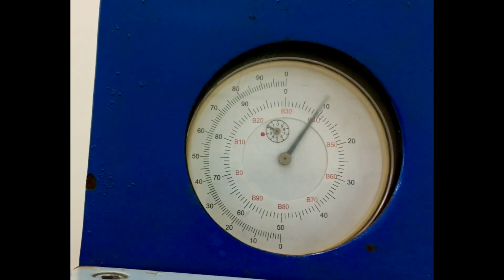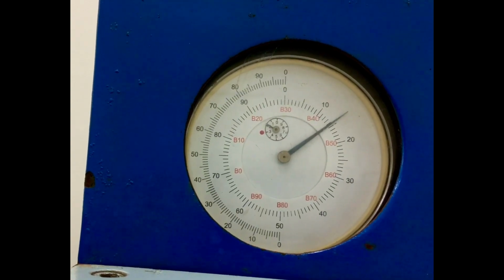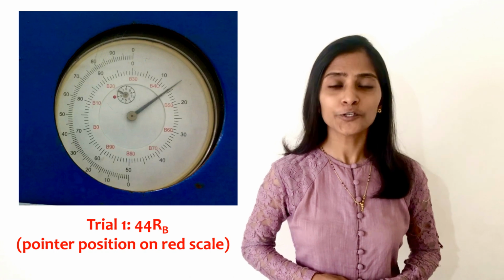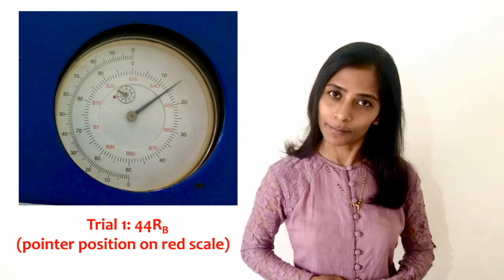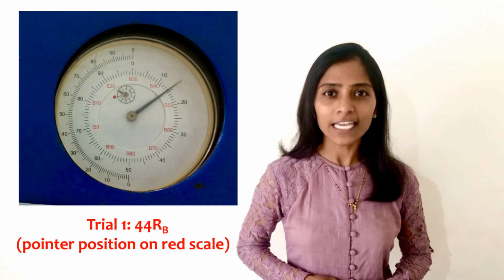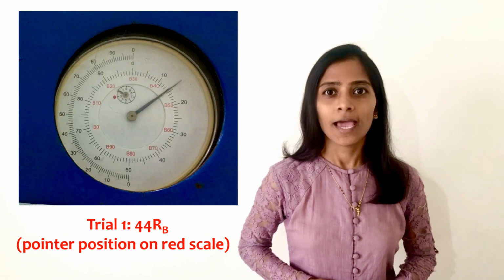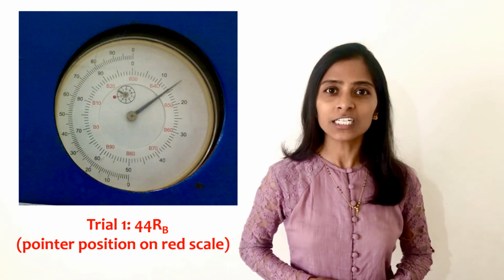After unloading, we have to observe the red scale carefully. According to the first trial, the hardness of the test specimen is 44 RB. We have to repeat this experiment 2 more times, and by taking the average of 3 trials, we will get the appropriate hardness for the aluminium test specimen.